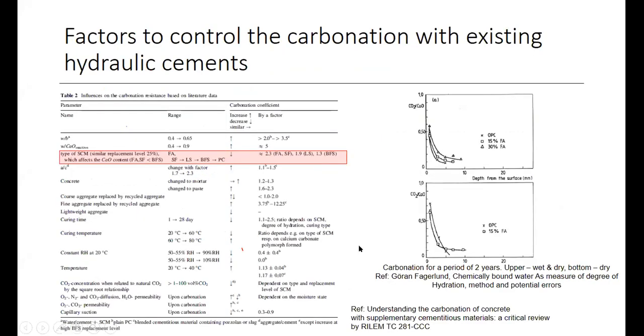Here you can see I have taken this from this RILEM research. You can see they are utilizing fly ash, silica fume, limestone, slag, and OPC. You can see fly ash and silica fume have about 2.3 times higher carbonation possibility than OPC, and limestone about 1.9 times higher than OPC, and slag about 1.3 times higher possibility of carbonation than OPC.